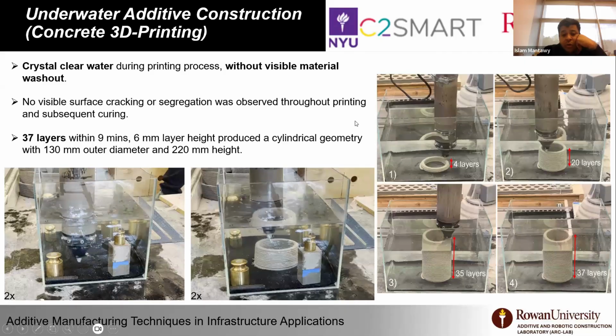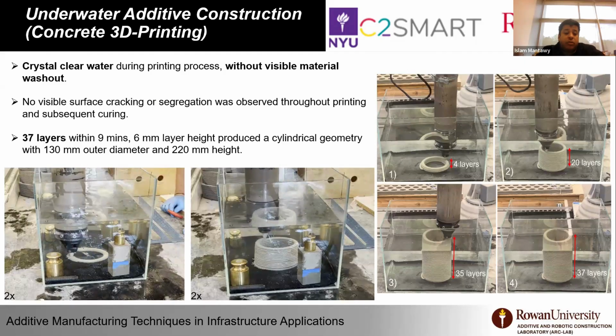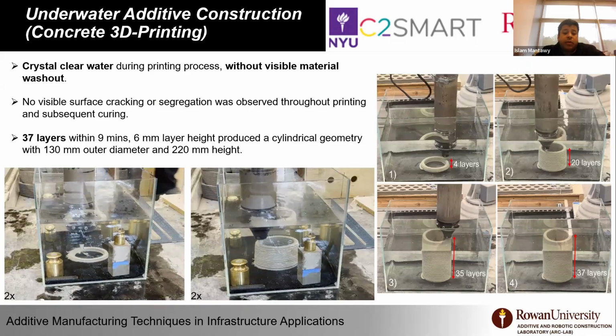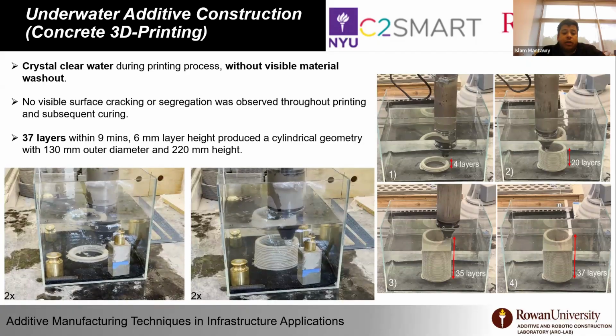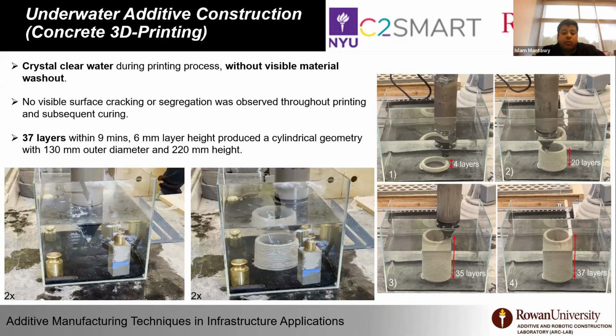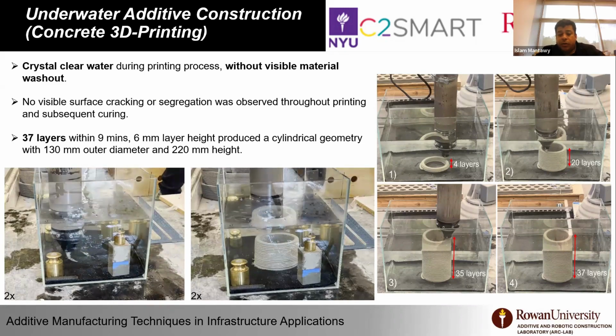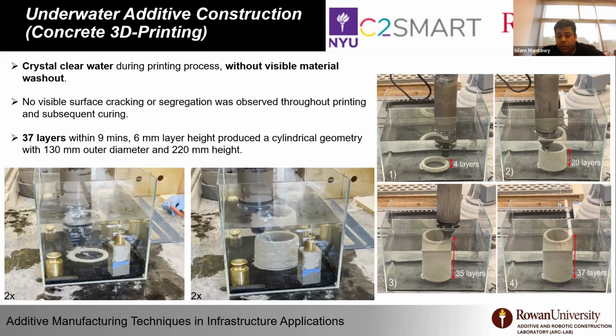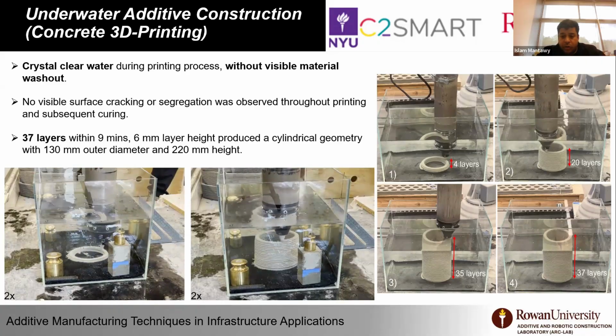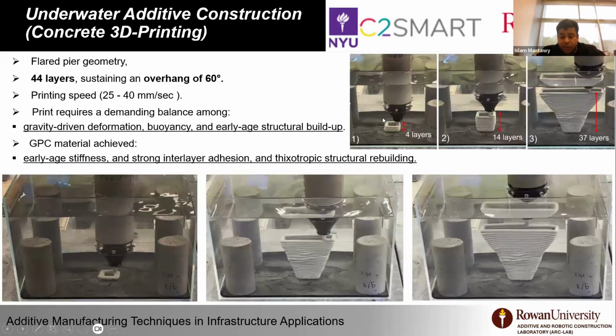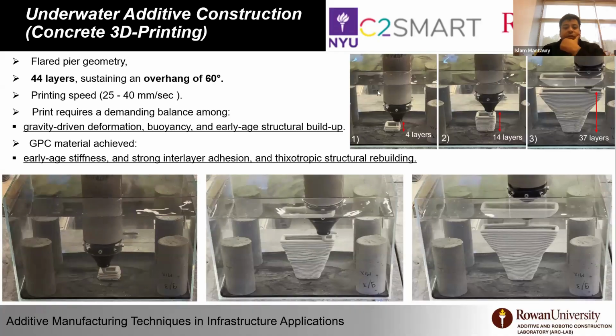We were also able to demonstrate that the material can be printed underwater. As you can see here, we have our own water tank filled with tap water, and we use the material and print underwater, which is a little bit challenging. I think we reached less washout compared to other materials in the market. Another demonstration was flared structures and the ability of the structure to withstand underwater. As you can see in the midway, we have some hiccups in the printing process, but it was able to continuously print even with some deficiencies.